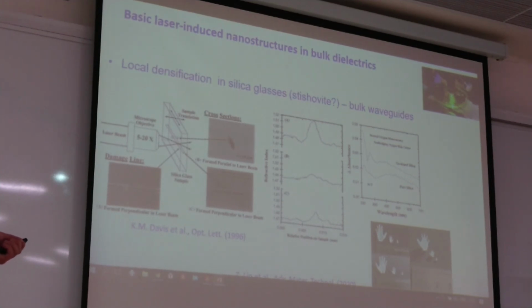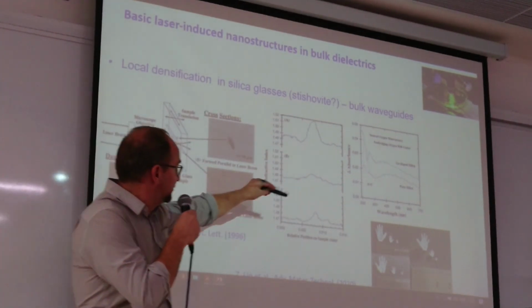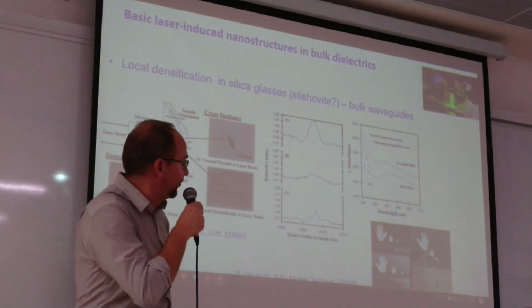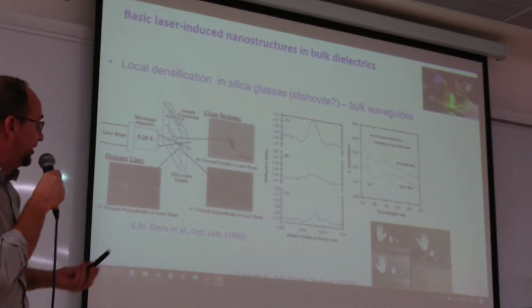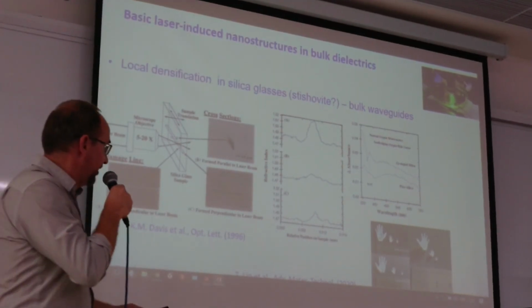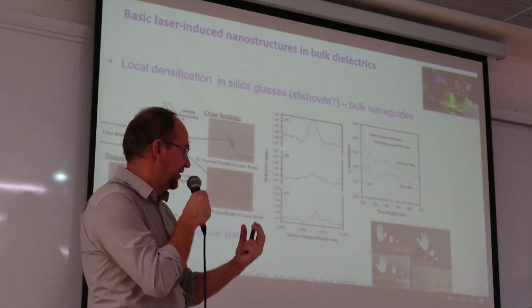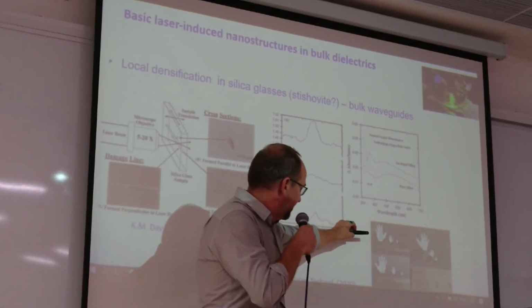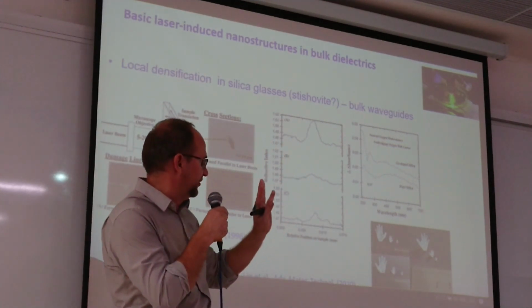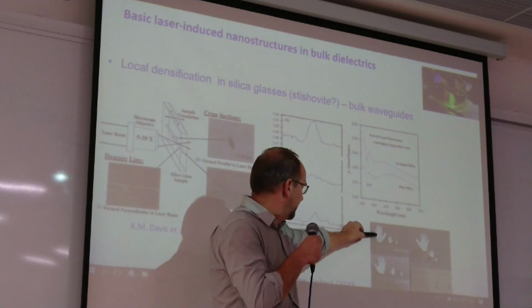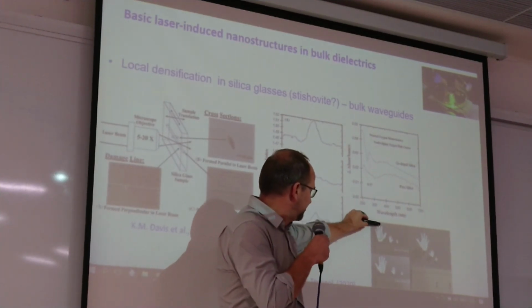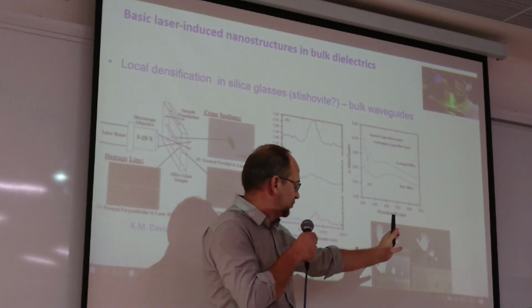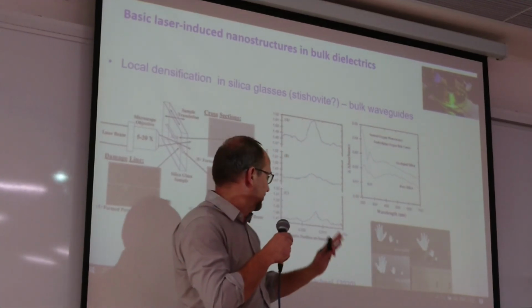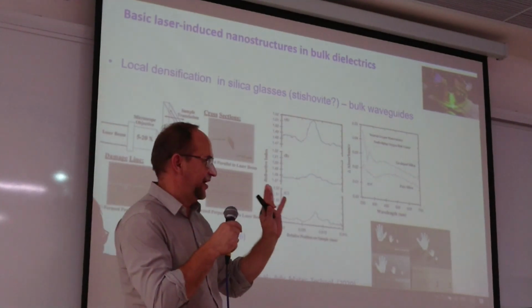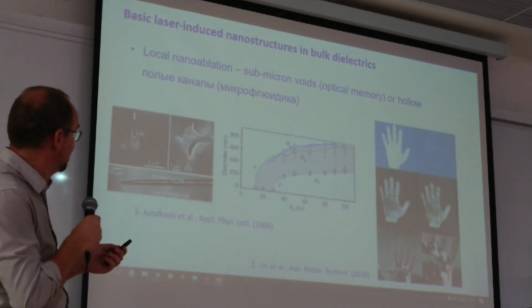Cross-sectionally, this is a more dense region. This is the refractive index profile, and it is related to modification of the oxygen matrix in silica glass, the changing of oxygen centers. And using this technology, people can densify glass, and for example, in a piece of glass, make local densification in the form of a hand. So this is a piece of glass with densified material in the form of a hand, and other glass was removed by etching. So there is a millimeter scale glass hand. And later I will show you something more interesting.